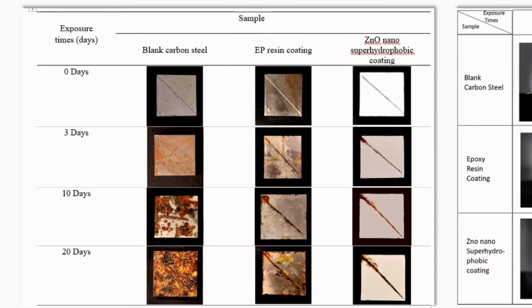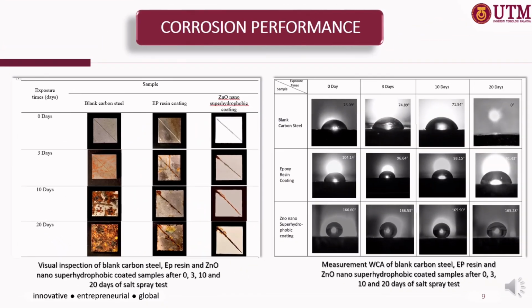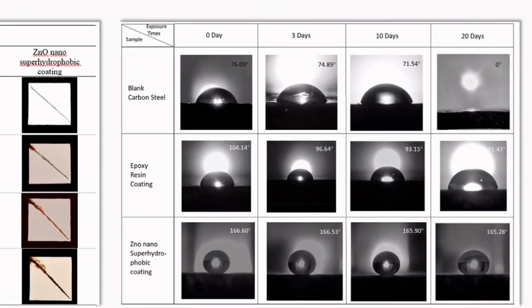However, EP resin exhibits a minimum amount of corrosion, but with a few blisters and peeling, while the zinc oxide nano superhydrophobic coated surface samples remain intact with absence of little rust on scratch marks, no peeling, no blister, and a completely clean surface after exposure. Based on the water contact angle reading trend, the zinc oxide nano superhydrophobic coating also maintains its superhydrophobicity even after exposure to a harsh environment, with 166.60 degrees before and 165.28 degrees after the testing.